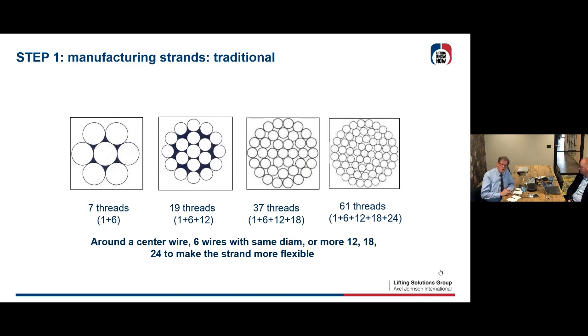If in the same diameter you need a strand which is more flexible, then you can start with wire which is thinner, and then you add another layer, like you can see there, 1 plus 6 plus 12. You end up with 19 wires in 1 strand. If that isn't flexible enough, you can add another layer, and then you have 1 plus 6 plus 12 plus 18. That's 37 wires in 1 strand, and you can add another layer. You can have 61. So it's more flexible every time you use smaller diameters of wire and put on more layers.